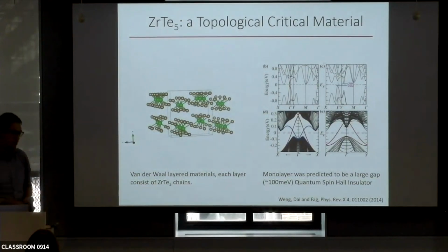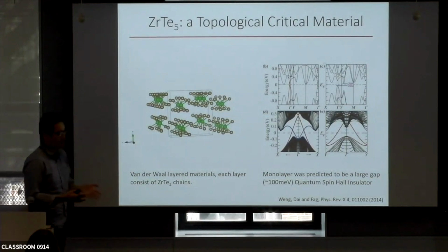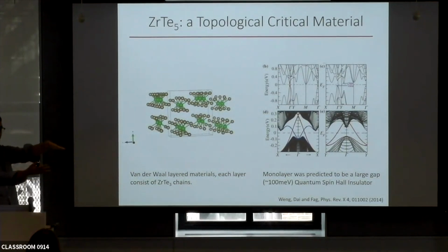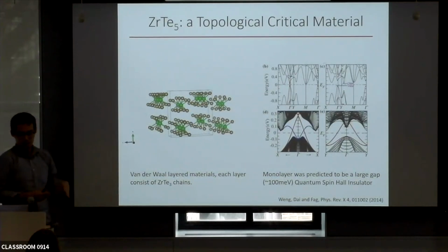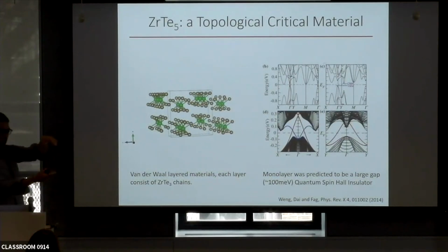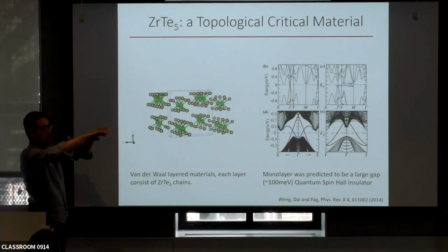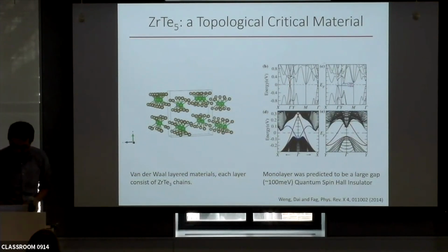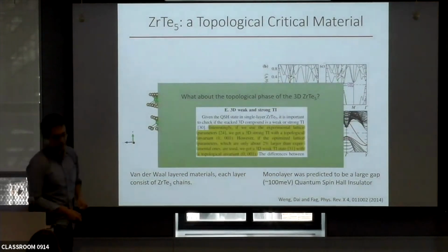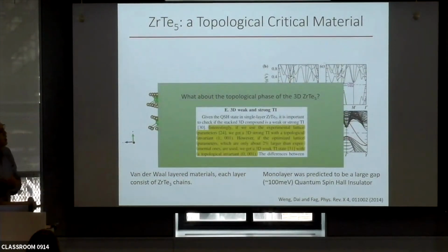As speakers discussed yesterday, one possibility is forming a weak topological insulator, right? You basically transform the edge states of the 2D layers into a 2D surface state on the side surface. But another possibility is that you can have an extra band inversion and eventually form a strong topological insulator with surface states on all crystal surfaces. They also did these calculations, but interestingly, they found that they cannot determine whether it is a strong topological insulator or a weak topological insulator.